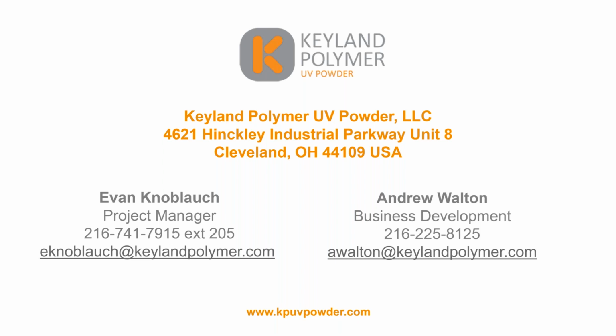Do you need to use plasma and conductive primers on all substrates with this technology? No, that is not the case. It's more for trial and error. The way we operate our projects is we'll be provided the substrate and run a feasibility test on them without any additional steps. Based on those results, we will apply a conductive primer or utilize plasma treatment technology.